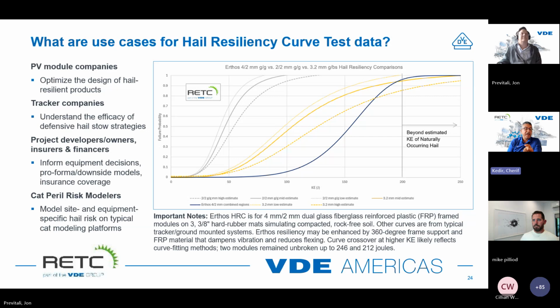So when we developed the HDT initially, one thing we noticed is the way we performed the testing: we always started in the central region, and then we moved to the perimeter and then the corner. And then our engineers always came back and said, hey, listen, I think we're weakening the glass by impacting it in the central region, and by the time we get to the perimeter and the corner, it was already too weak. And so one thing we started doing is reversing the order, and we found that if you impacted glass in the corner, it was just more likely to break. So that's right. Absolutely a very important finding. And we had to learn it from scratch, but that's a really, really important aspect of the testing.